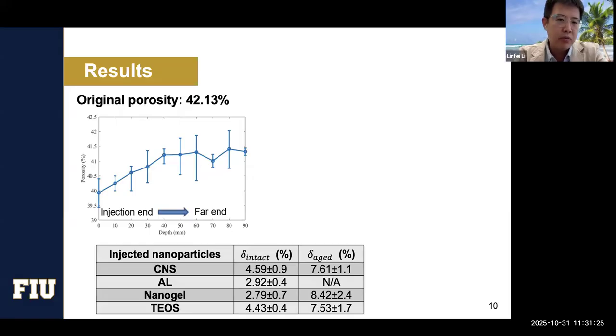As you can see, we have a pretty clear trend. If you are close to the injection end, there was more than 2% porosity decrease. But if we look at the percentage, as you can see for the intact sample, the colloidal nanosilica shows the best performance. And for the aged samples, it's different.